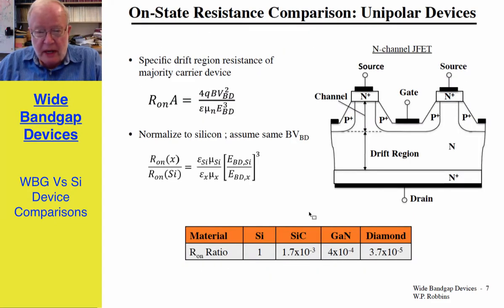Going forward, if we do a comparison of the on-state resistances, the figure of merit is usually the on-state resistance times the area of the device through which the current is flowing. This is the so-called ohms per square. And if the drift region is the dominant factor in on-state losses, it's fairly simple to show that an approximate formula for the on-state resistance is given by this formula. It's proportional to the square of the breakdown rating and divided by the cube of the breakdown field strength.